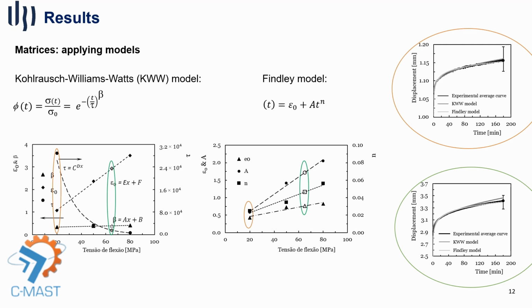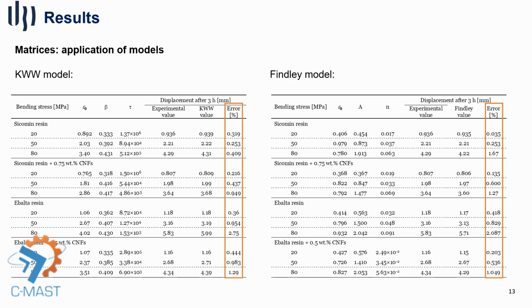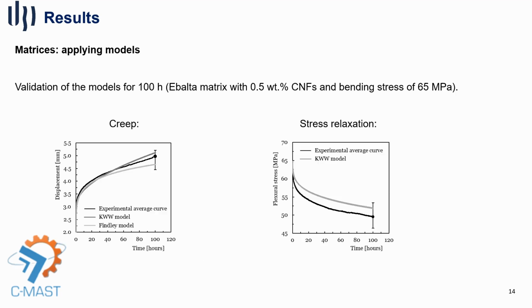Two mathematical models were applied, Kohlrausch-Williams-Watts (KWW) and Findley, in order to predict the behavior of the matrix at given loads as a function of loads applied. Good results were obtained within the range of the dispersion values and with fairly low error. Similar tests applying the same models were carried out for 100 hours, trying to predict the material behavior based on the 3-hour tests. We can see the theoretical results were within the range of the practical results.